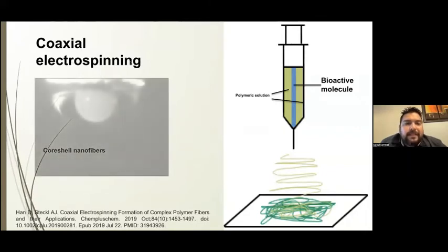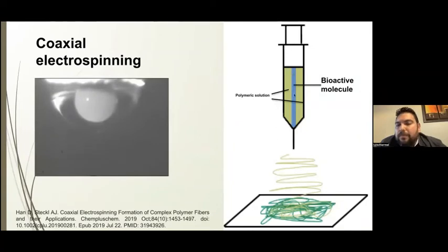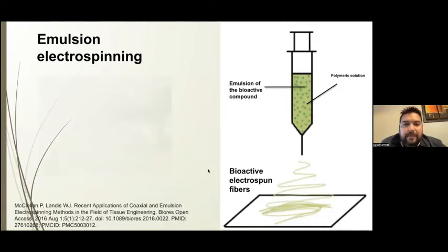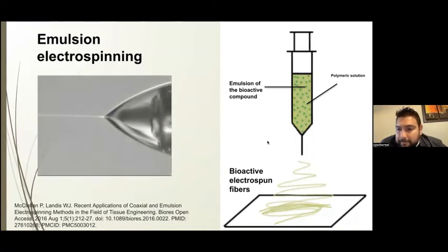You can also have coaxial electrospinning, where you use a special syringe with two holes. In the inner hole, you have the bioactive molecule, and in the outer hole, you have the polymeric solution, and this is intended to protect the bioactive molecule from the environment, since it can be labile to temperature, light or electricity. You can also prepare nanoparticles or nanogels or other molecules that don't dissolve into the polymeric solution and create an emulsion system. And then you load it, and you can have fibers with these kinds of nanoparticles on the surface of the fibers.